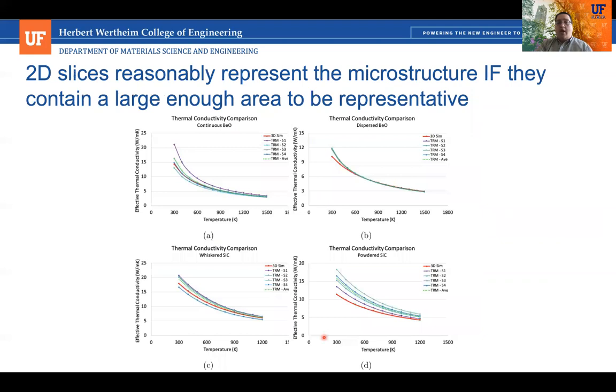And what we did is we would take a 3D microstructure and calculate its effective thermal conductivity, and then randomly take multiple slices of that 3D microstructure and make images of it, and then use the thermal resistor model with the genetic algorithm to estimate the thermal conductivity of those different slices. And we compared them against the 3D simulation. And in general, there was some scatter between slices, but it was not large, and they overall compared well with the thermal conductivity from the 3D simulation. The one exception to that was the same powdered silicon carbide microstructure where the model itself didn't perform very well compared to the experiments.